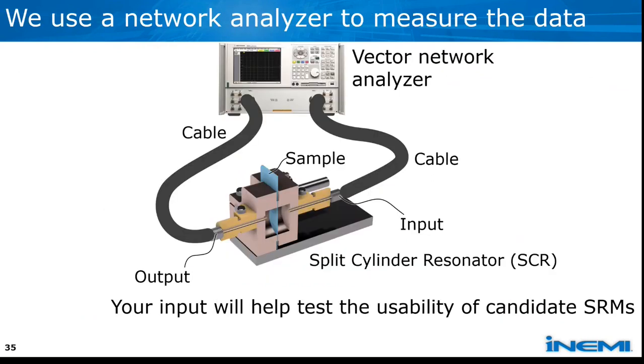So when we measure the split cylinder cavity, the way that we do it is with a network analyzer. If you're unfamiliar with that, you can think of it as just a thing that's sending a signal from the left through that black cable into the cavity, and it's resonating like a note on a guitar or a harmonic on a guitar. And then at that resonance frequency, a signal can propagate from the left to the right back through that black cable up to that vector network analyzer. And that allows us to measure the transmission through the cavity.